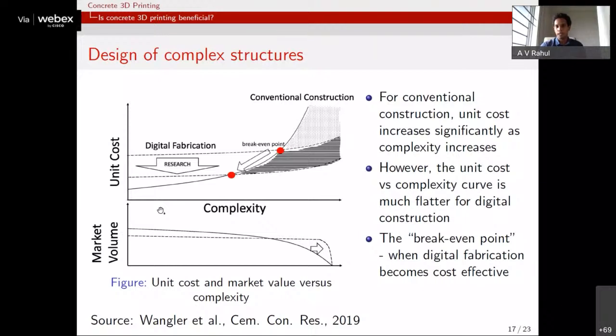So if you have a more complex structure, as complexity increases, here you can see this dark line shows the conventional concrete, and this dotted line shows what you obtain through digital fabrication. So if you are looking at a less complex structure, mostly a rectilinear type of structure, then you see that because the mixture cost for 3D printing is quite high, digital fabrication may be quite a bit costlier than conventional concrete. But when you have some more complexity in the structure, let's say you have to do a curved element, or you have to do some other complex type of geometries, there you see that the conventional construction becomes significantly more expensive.